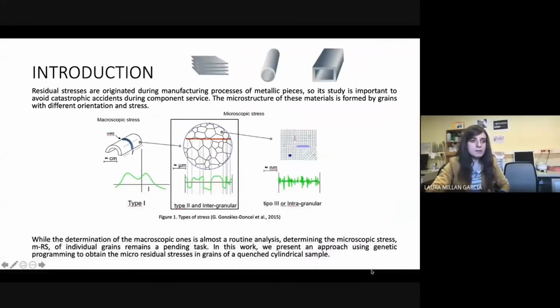This project studies the residual stress that originates during the manufacturing processes of metallic components. Its study is important to avoid catastrophic accidents because these stress fields are retained inside the materials after the treatment. We can find two types of residual stress, macroscopic and microscopic stress. The first are related to the geometry and the features of the piece. However, microscopic stress depends on the microstructure and the mechanical behavior of the grains. It's important to know each grain can present a different behavior according to its orientation.